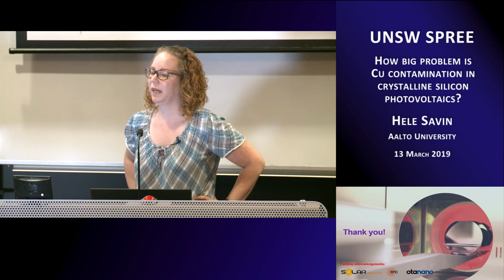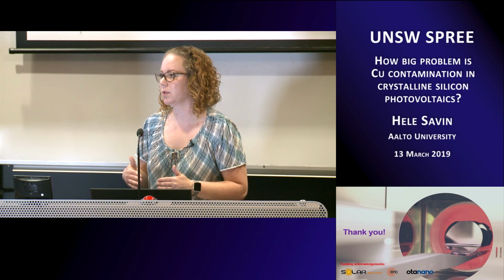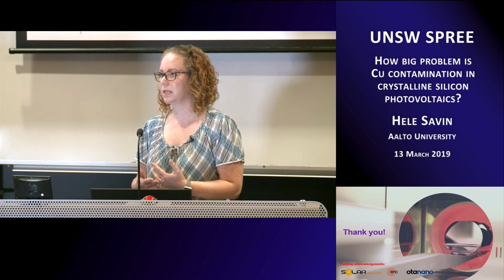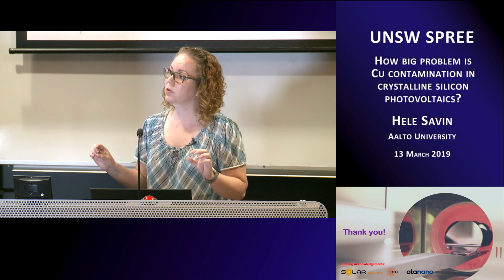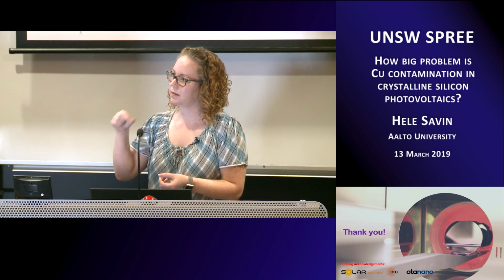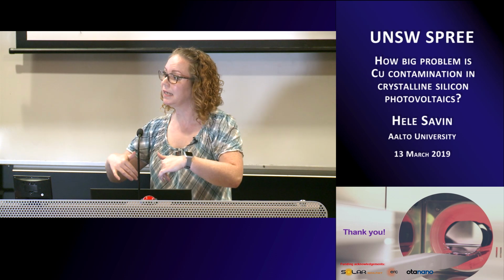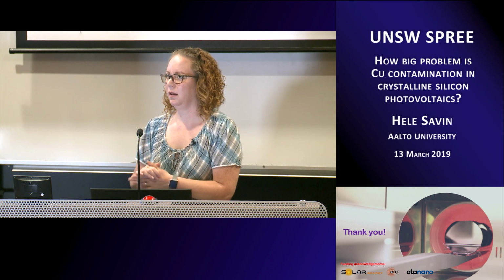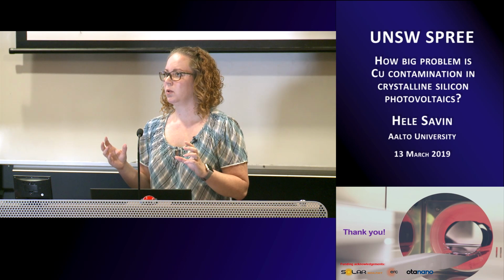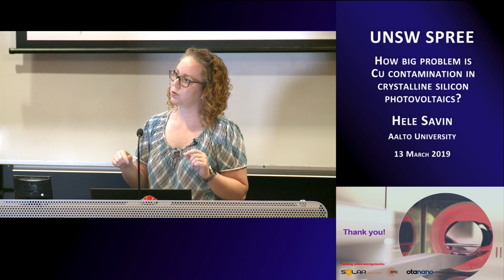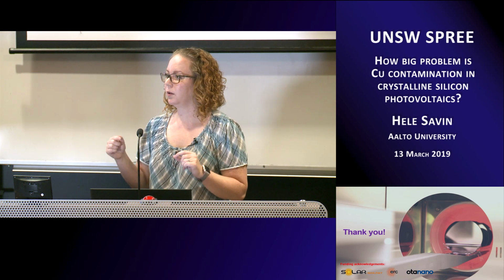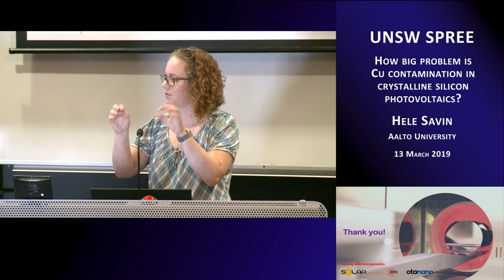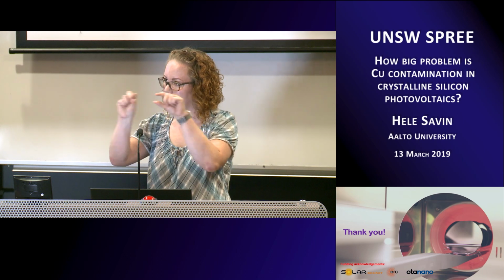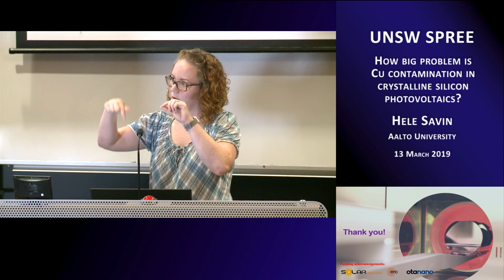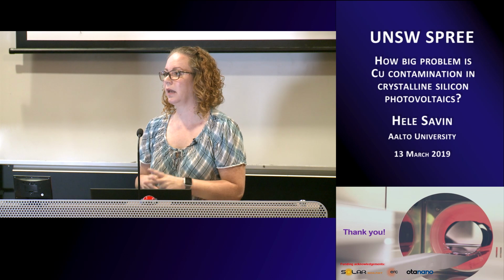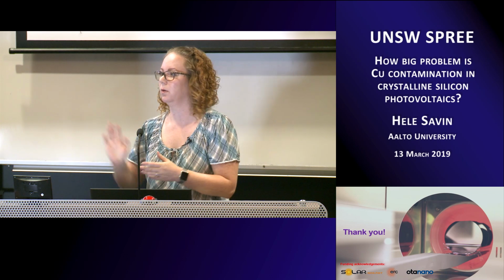So they were done at wafer level, really in the beginning of the process. What we usually do is we grow some thermal oxide, then we put the copper droplets on top of it, then we diffuse it in through the oxide. It is well known that no other impurities diffuse through the oxide at those temperatures except copper. Otherwise, if you did that on a bare surface, you would end up driving in all these different types of impurities. So we always do it on high quality thermal oxide so that we know it's only the copper that goes in. And then we remove the oxide and do the normal PERC processing.